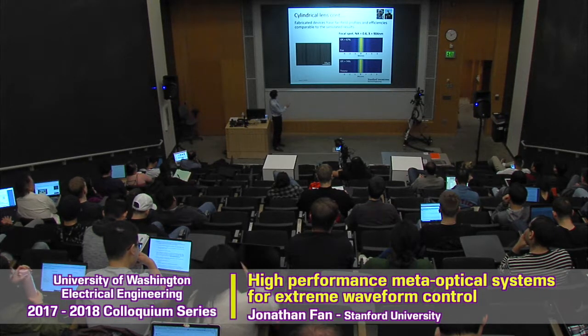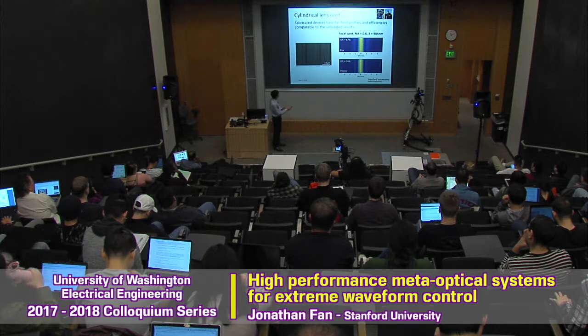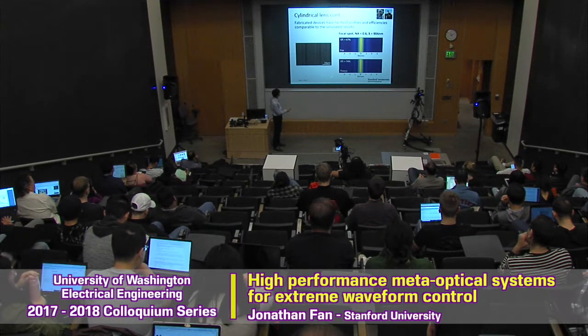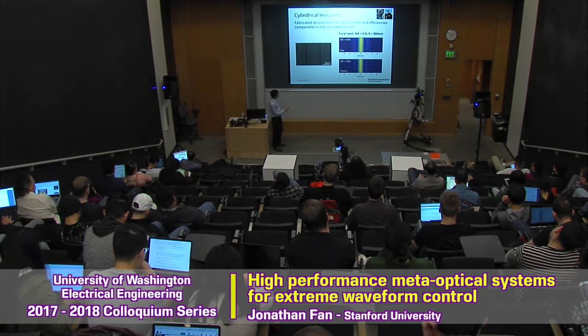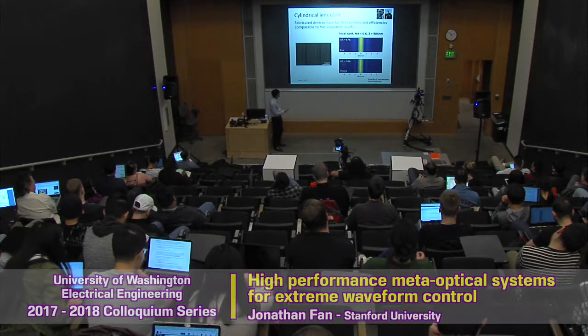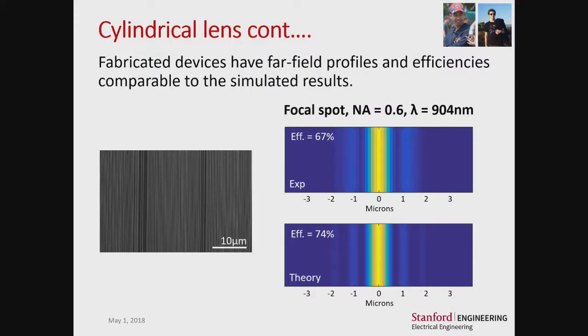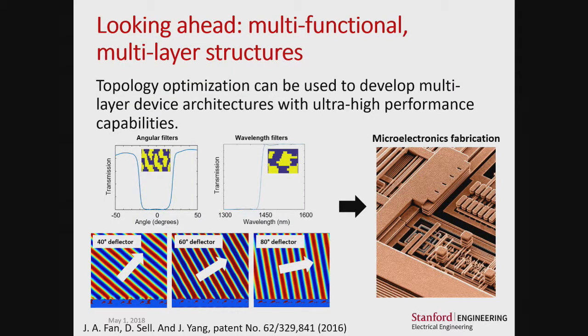Here we have, for these fabricated devices with an NA of 0.6, pretty good agreement between theory and experiment, where we have devices that have focusing efficiencies within 10% of theory. And we're currently looking to push this to the large NA devices, where actually the challenge is figuring out exactly how to characterize these, because we're pushing the limits of conventional off-the-shelf optics. And this perhaps reflects some of the opportunities for meta devices to make high-efficiency large NA devices that do not necessarily exist in practice. Looking ahead, I think the direction that this really needs to go is ultimately to multi-layer